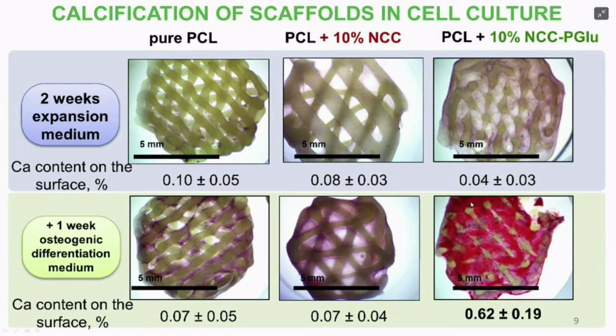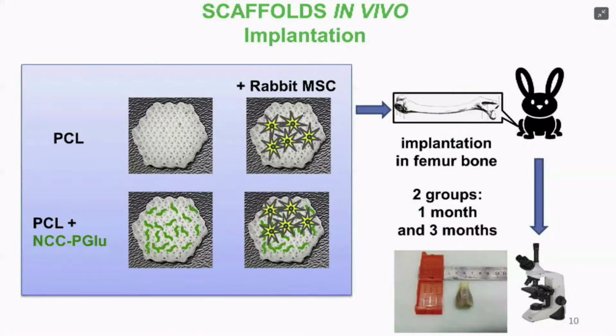And the intensity of red staining after the Alizarin Red S staining also tells us the same results, that the first 5 samples have traces of calcium, but the sample with the polyglutamic acid attached to non-crystalline cellulose provides the best results. So after the test with cell culture, we proceeded to the tests in vivo. With the help of our colleagues from the Institute of Physiopulmonology of St. Petersburg, we performed the implantation of scaffolds in rabbit femur bones.